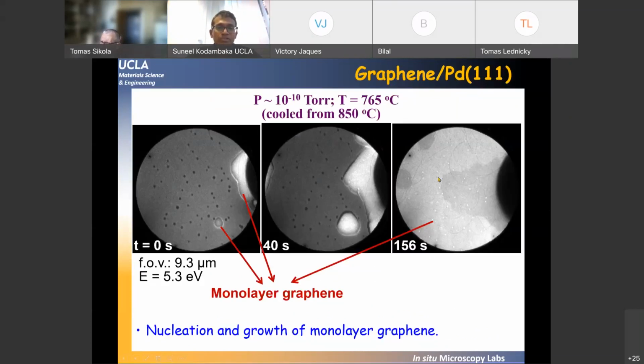So in the LEEM movie that you're going to be watching, you will see this nucleation and growth of graphene islands, monolayer graphene islands, which will appear brighter compared to the relatively darker background, which is the palladium surface. And you will also notice these finer changes within the contrast, and that's because of the presence of different rotational domains of graphene growing on palladium.